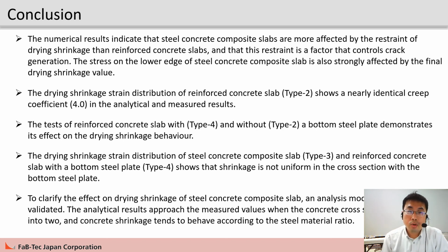The test of reinforced concrete slabs with type 4 and without type 2 a bottom steel plate demonstrates the effect on the drying shrinkage behavior. The drying shrinkage strain distribution of the steel concrete composite slab and reinforced concrete slab with a bottom steel plate shows that shrinkage is not uniform in the cross-section with the bottom steel plate. To clarify the effect on drying shrinkage of the steel concrete composite slab, an analysis model is proposed and validated. The analytical results approach measured values when the concrete cross-section is divided into two, and concrete shrinkage tends to behave according to the steel material ratio.